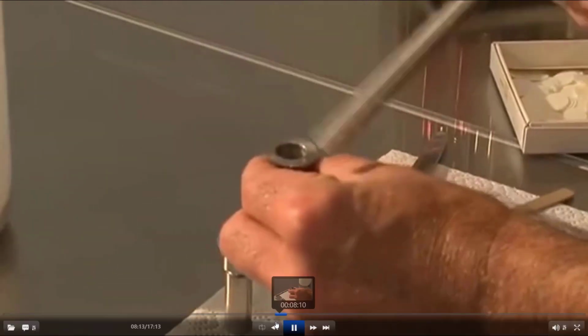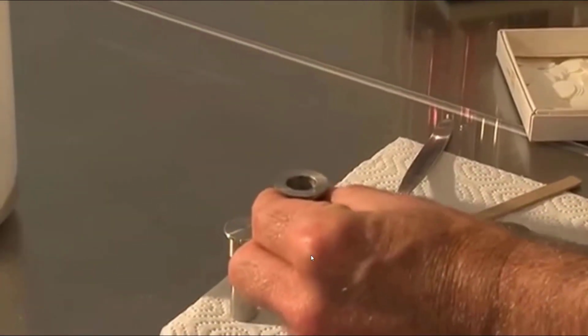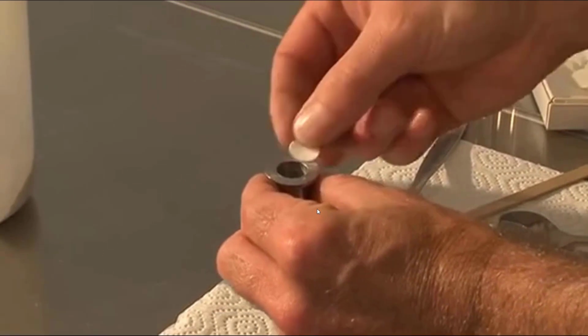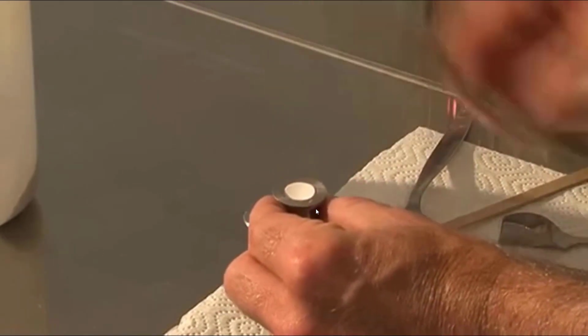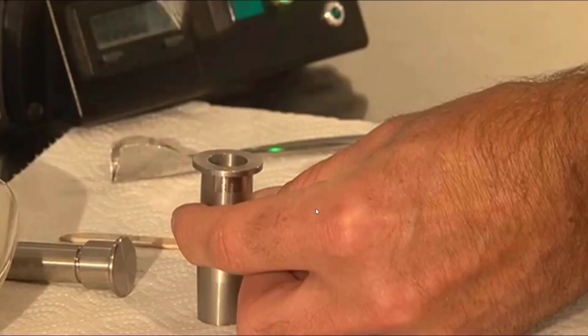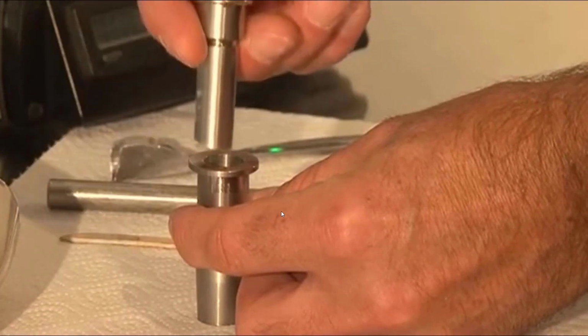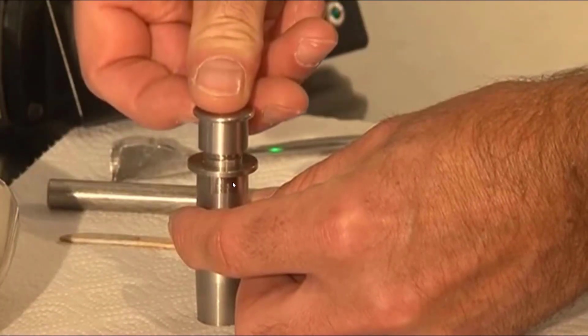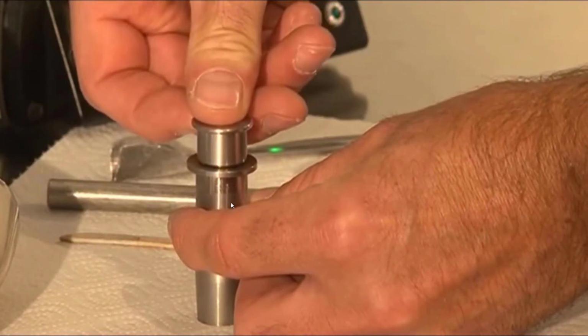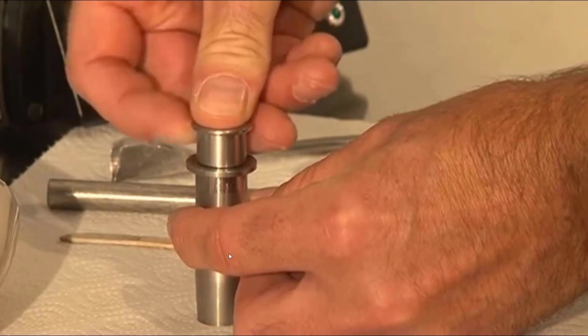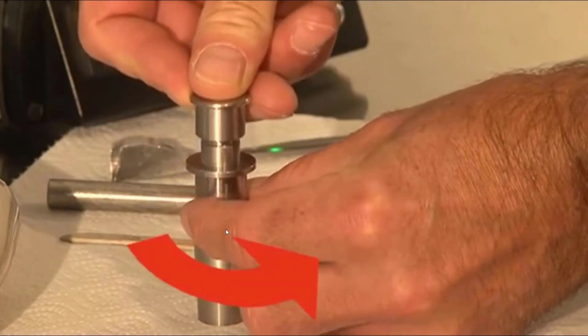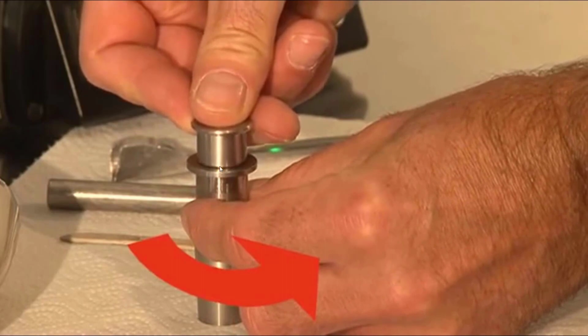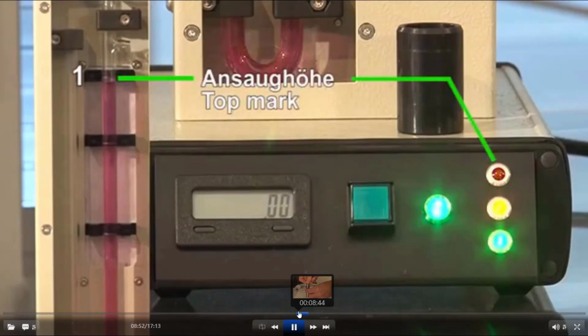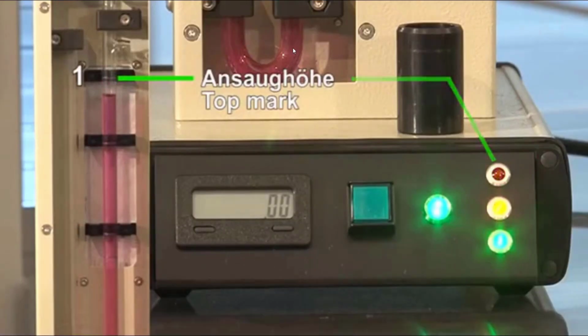Then you will insert the plunger and compact it well, so that the air present between the cement particles is released. As the cement grain size is too small, there might be some air present in the cement particles that must be released by inserting the plunger and rotating it. Then, after placing the cell